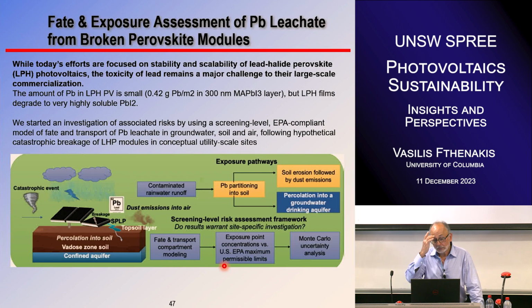So it's a small amount, but nevertheless, the methyl ammonium lead iodide, when it degrades, forms cations, MAI perhaps, and also lead iodide. Lead iodide is very, very, very soluble. We're talking about many orders of magnitude more soluble than lead from solder or cadmium from cadmium telluride. Many orders of magnitude more soluble. So there is an issue there.